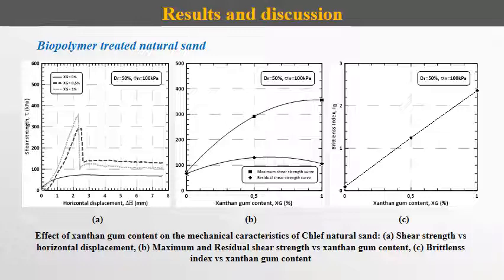Figure C presents the influence of xanthan gum content on the brittleness index of Chlef sand. It is noted that Chlef sand brittleness index increased with an increase of xanthan gum content. As previously stated, biopolymer treatment increases Chlef natural sand rigidity, which in turn increases the soil brittleness. This brittle behavior is accentuated at higher xanthan gum contents.